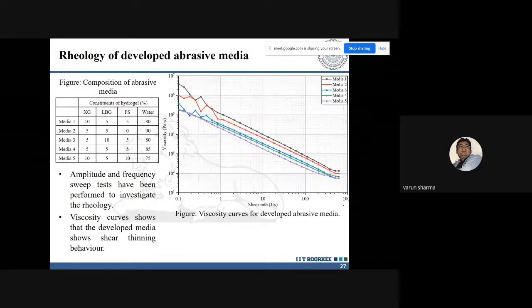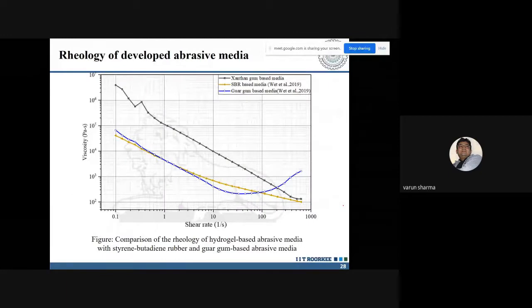So that was not holding up the abrasive particles with temperature, but our media was showing a better shear thinning behavior as compared to the other. So you can see over here, this was the shear thinning behavior, this camel color is for the synthetic rubber. This was for our case, and this was another media that was being developed in the literature, a guar gum based abrasive media.